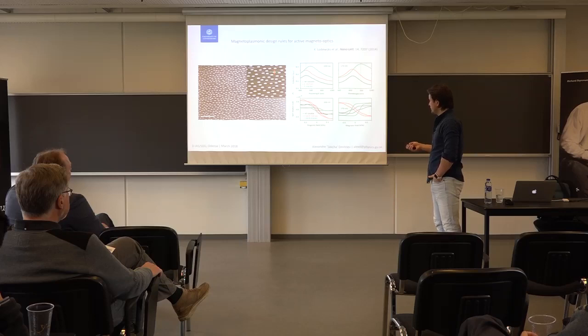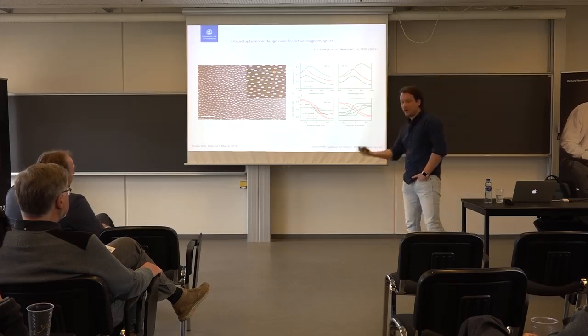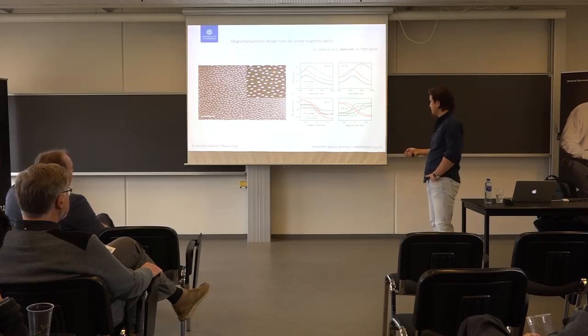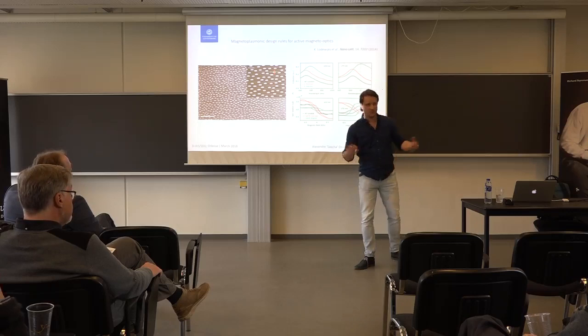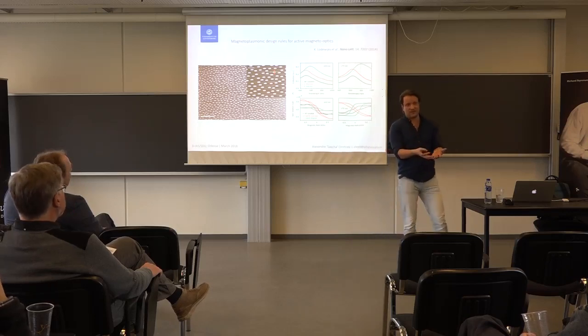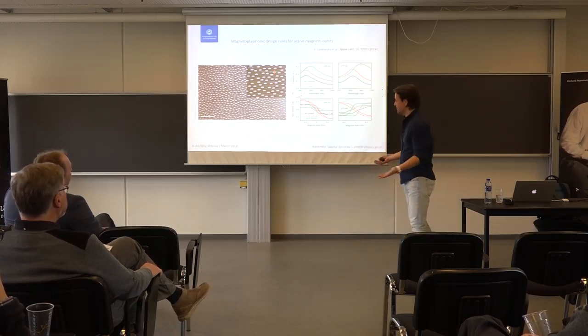And you can see that depending on how you come with the original polarization of light, here green or red, or something in between, this is just a disk, so there are no axes, you form a completely different amount of polarization rotation. So this is like a cheap way of creating a tunable optical system. You just apply a magnetic field to a ferromagnetic antenna, and you get a different polarization rotation as the outcome. So that's your real-time tunable system.